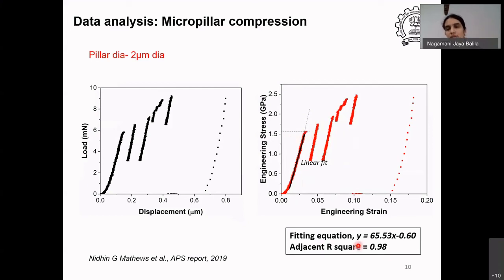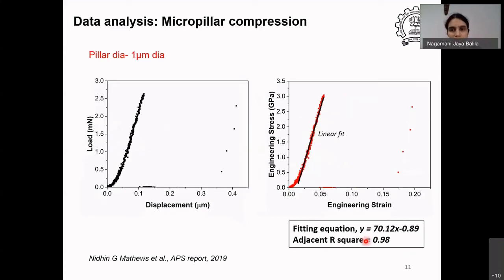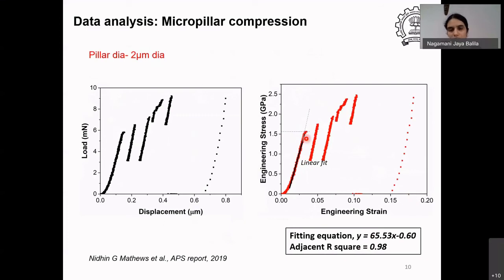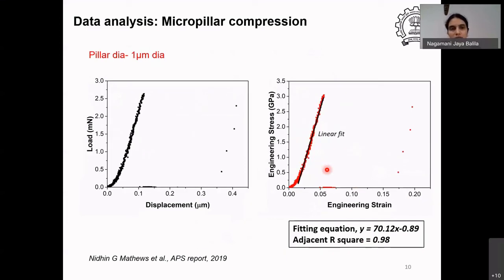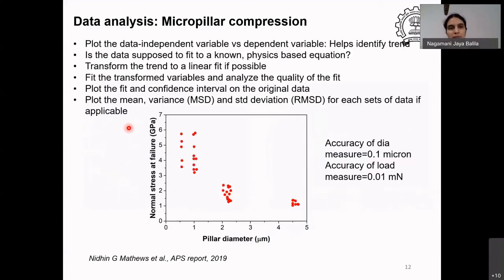You can choose the region which is completely linear, then extrapolate it, and the point at which the actual curve deviates from that linear fit is taken as the yield strength. You can get a fitting equation and do this in your R session. The fit for two microns looks like this curve; for one micron the noise becomes higher because the loads the instrument is measuring are now lower, so there are ways to smooth the data if needed.